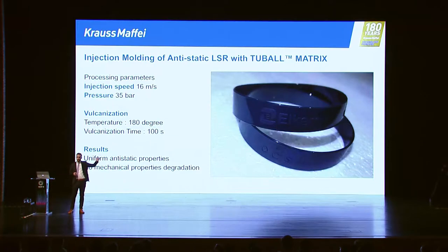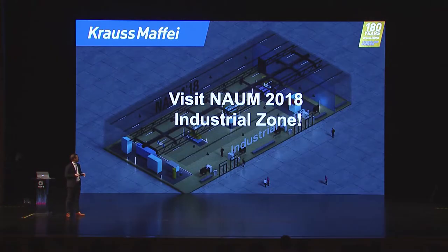And coming back to APC plus, this is a function we normally use if we have large amounts of viscosity changes for this material. We still activate it to get an even higher shot weight consistency, but we wouldn't even need it in this case. So thanks to the Tuball material, really a very stable and robust processing of LSR materials is possible.